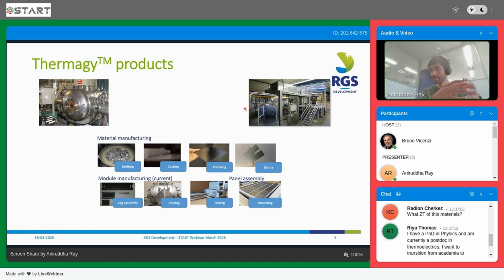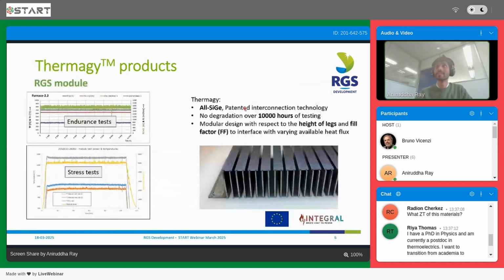Talking about the upscalability, indeed, if you want to make something which can actually fly in a real application, you need to make sure that the production process can be tuned in such a way that the costs are low enough. After we produce these devices, we do extensive testing. Here you can see some of the tests that we have done with our all silicon germanium-based modules. We carried out endurance tests, testing up to 10,000 hours at 600 to 700 degrees centigrade. It's able to generate around 2 kilowatts of electricity per square meter.